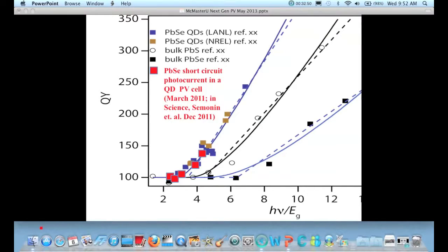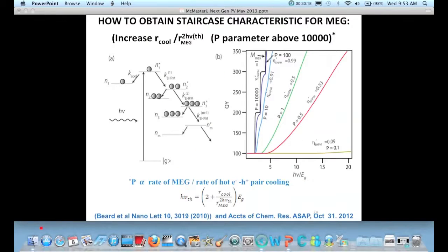When you correct for reflection and model the absorption characteristics of the quantum dots, you'll see that it matches the optical spectroscopic experiments. And so that's satisfying, and it means if you do the optical spectroscopic experiments correctly by having a dynamic experiment, you can get the right result, which is consistent with the photocurrent measurements.